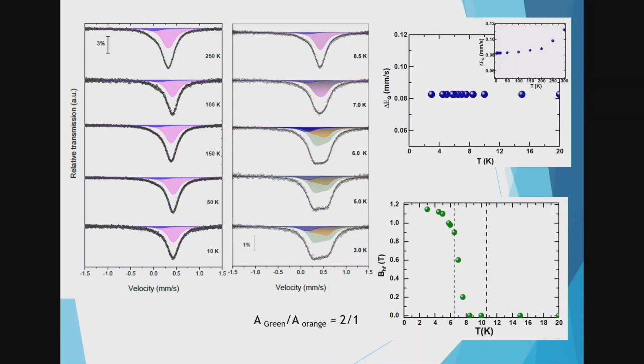I see. And I assume that iron is iron 2 plus. Iron 2 plus, yes. For instance, I measured this with Edson sometime, and I prepared the sample with 1% of iron. And it was nice, Edson. We could not find the best fitting anyway. So I put iron 57, and the spectra were very good, but this spectra is not easy to fit.